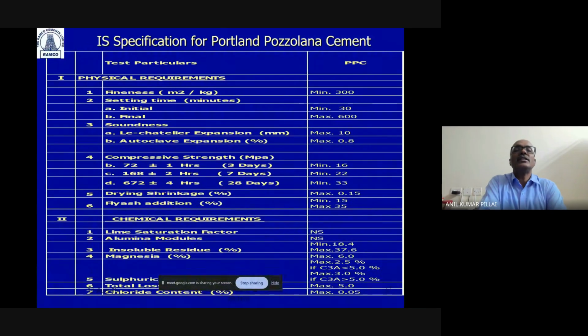And if you look at the test report of Portland pozzolana cement, the fineness would be higher. It would be close to 300 square meters per kg, whereas for ordinary Portland cement, the limit is stated as 225 square meters per kg. The basic idea is that if you have a higher fineness, the reactivity would be much better. And again, for Portland pozzolana cement, you will have initial and final setting time, Le Chatelier expansion of maximum 10 mm, autoclave expansion of maximum 0.8 percent. Then you have the 16, 22, 33 MPa strengths as mentioned in the code, but we can always enhance the compressive strength of cement through various other measures.